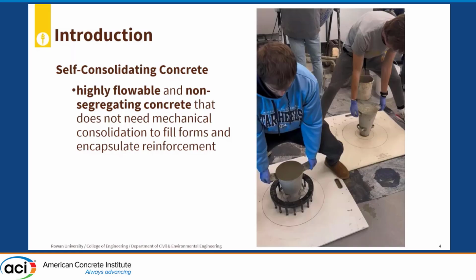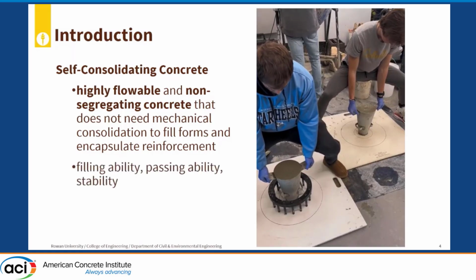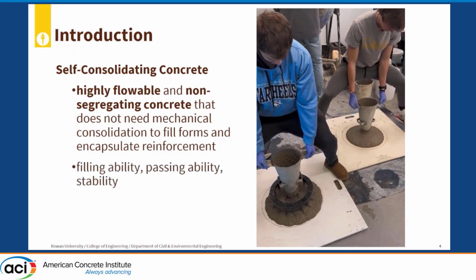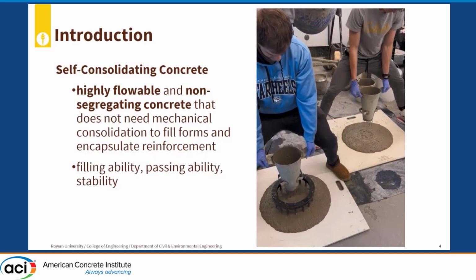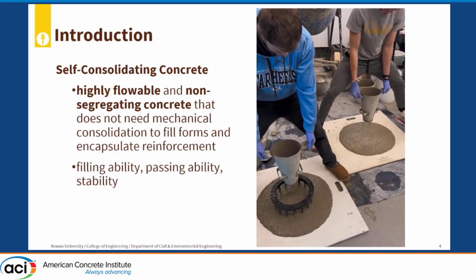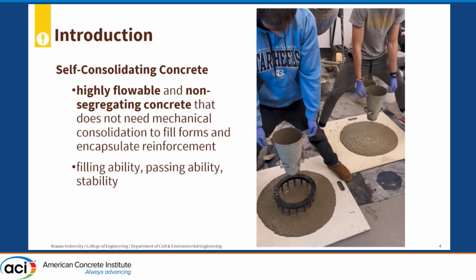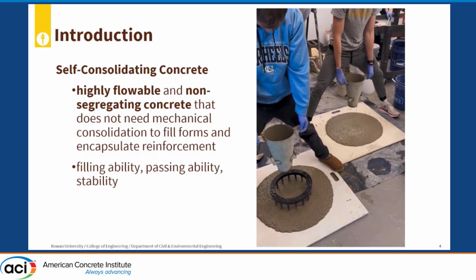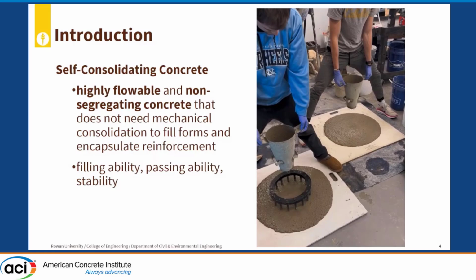So what is SCC? SCC is a highly flowable and non-segregating concrete that does not need mechanical consolidation to fill forms and encapsulate reinforcement. It has excellent filling ability, passing ability, and stability. On the video on the right, here are the tests for SCC. On the right is the slump flow test, and on the left is the passing ability test, or the J-ring flow test. So basically, we measured the diameter, and that describes how workable your SCC is. This one has a J-ring on it.